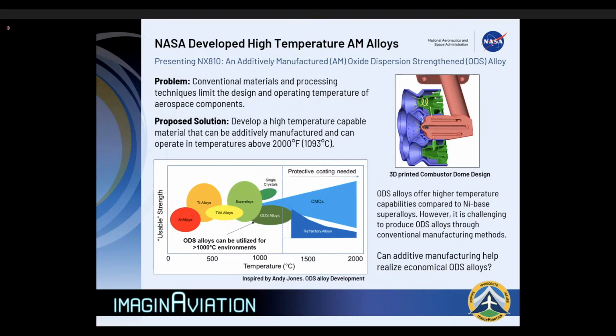This project really came about through a conversation I had with combustion engineers across the center, where they wanted to 3D print new combustor dome designs, with nozzles. So really complex channels and cooling surfaces, and it's something that you can't produce with conventional machining. And so they reached out because they were having issues being able to print a component like this that could operate at extreme temperatures, 2,000 degrees Fahrenheit or higher. And they said, hey, is there a metal that we can use to print to make these components where it won't crack and fail almost immediately after testing?